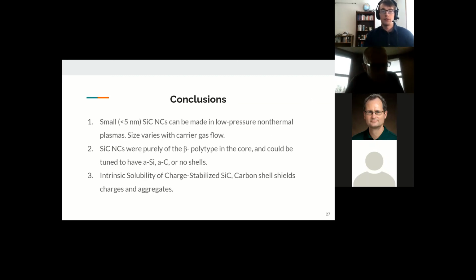The TMS precursor had excess carbon that was consumed by hydrogen in the plasma, which engendered a stoichiometrically balanced end result. If the exact amount of hydrogen was not added to the unbalanced precursor, the powder ended up either carbon or silicon-rich, which formed an amorphous shell around the particles. The carbon-rich nanocrystals were soluble in short-chain alcohols, and the silicon-rich nanocrystals were not. The optical band gap of the nanocrystals was measured to be 2.4 electron volts, which was the same as the bulk polymorph.